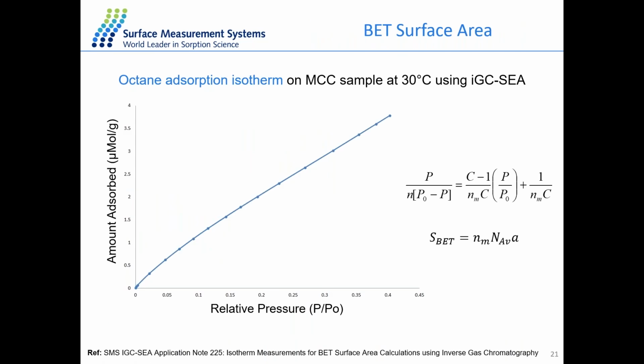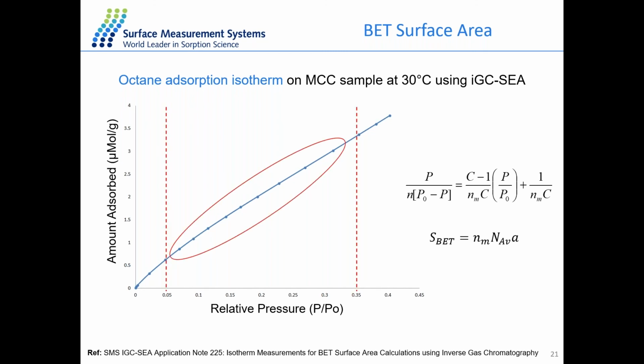But in this presentation, I just want to focus on the BET surface area of the microcrystalline cellulose sample. And the experiment we perform is just an octane isotherm at 30 degrees on the microcrystalline cellulose material. So here we use octane as the probe molecule. And according to the BET theory, if the shape of the isotherm is a type 2 or type 4 isotherm, which represents the monolayer formation mechanism, then we can use the points inside the BET range between 0.05 to 0.35 for the monolayer formation to calculate the BET surface area of the sample of interest.